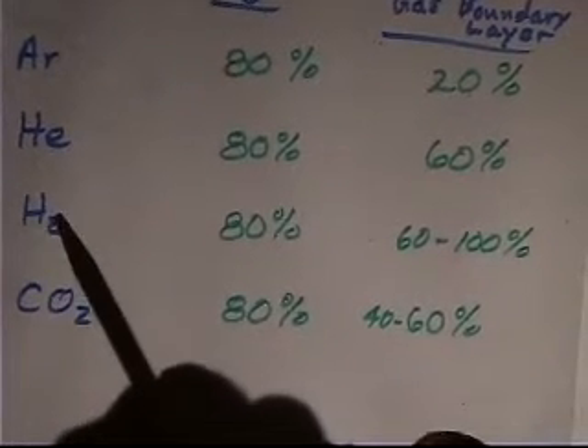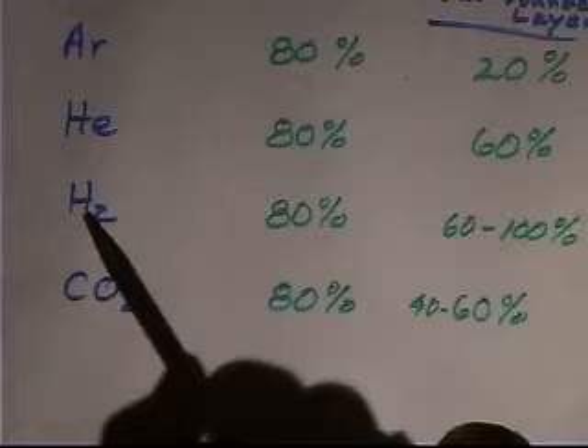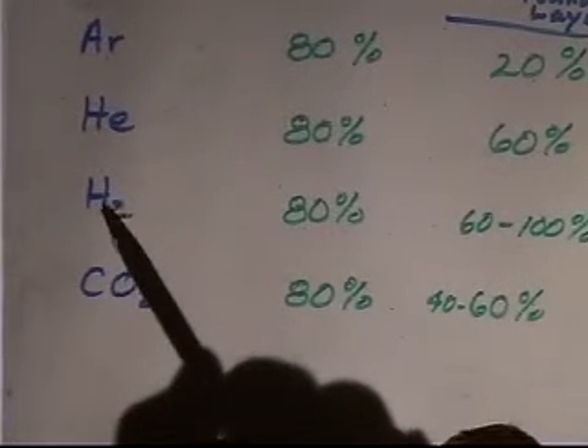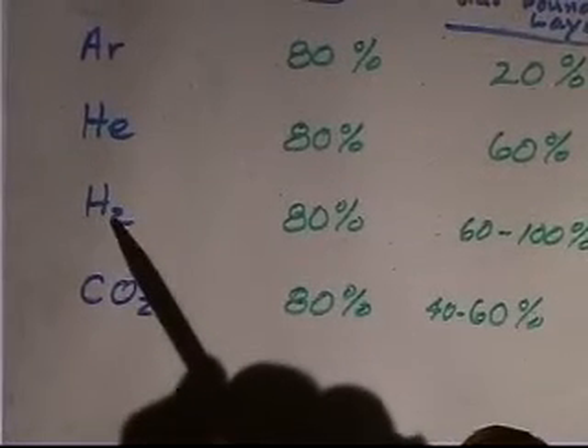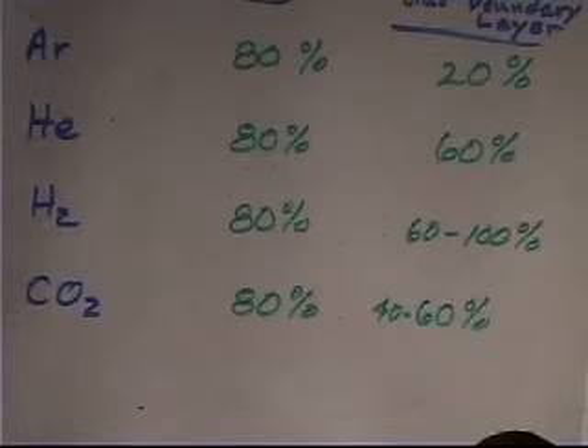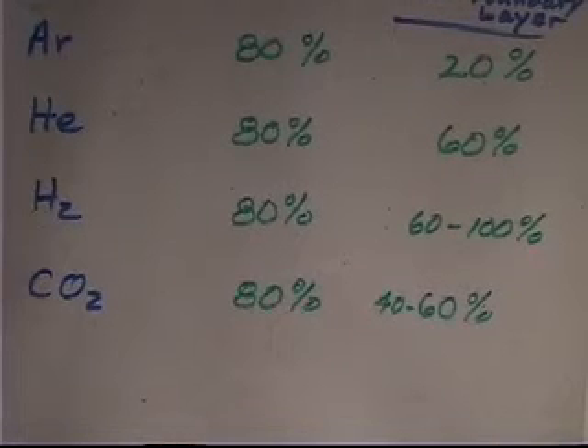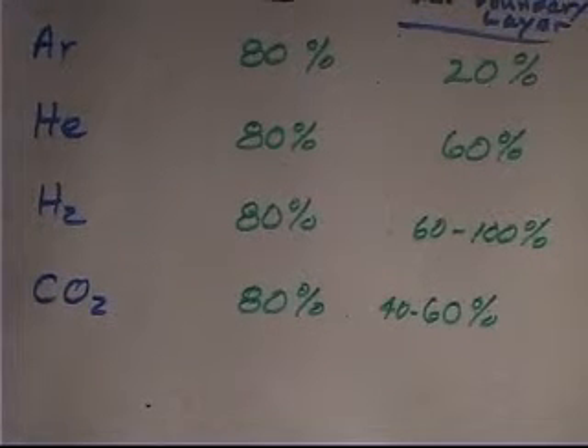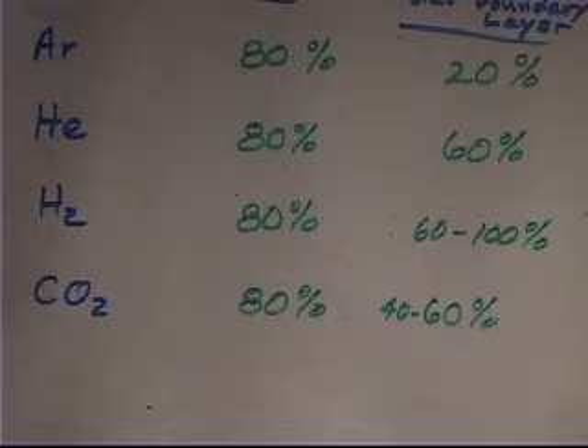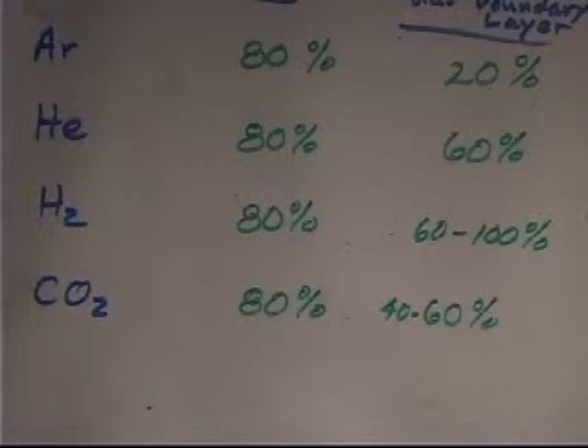People around the first half of the last century did weld with 100% hydrogen. They actually took a little electric arc and they blew straight hydrogen at that, and they struck the arc and they got a very, very hot flame. You could get 5,000 watts per square centimeter with these flames. You actually weren't getting the electrical energy into the workpiece, so you didn't have the electrical flow. You just had a very hot flame between 2 electrodes.